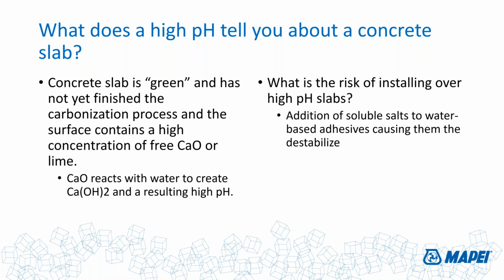And again, what are the risks of installing over a high pH slab? The addition of soluble salts to water-based adhesives can cause them to destabilize. And I know for any of you who have worked with SBR-based latex adhesives for the installation of broadloom carpet, this high pH concrete slab is notorious for causing destabilization, and the end result, like people say, is balling and stringing underneath the trowel. Why is that happening? Is it because the high pH is dissolving into the adhesive mix, changing the pH of the adhesive itself, causing it to destabilize, and it clunks out of solution, and you wind up with a mess on your hands.